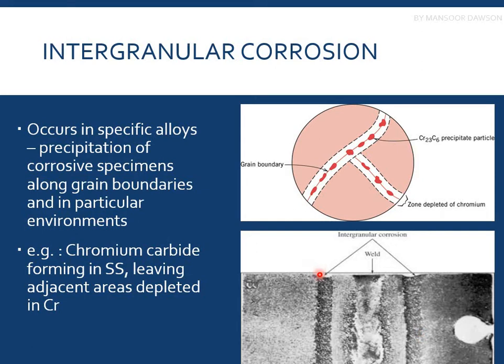Why does it have intergranular corrosion? Because this part has been soaked for a couple of minutes at the sensitization temperature of stainless steel, which is around 550 to 800 degrees centigrade. So you can see that here you have intergranular corrosion, in which you will have the brittle complex carbide precipitates, and the part would fail from the grain boundaries, not from the grain.